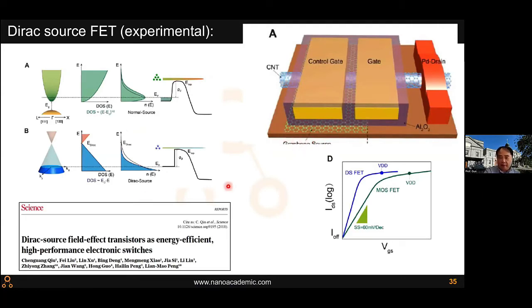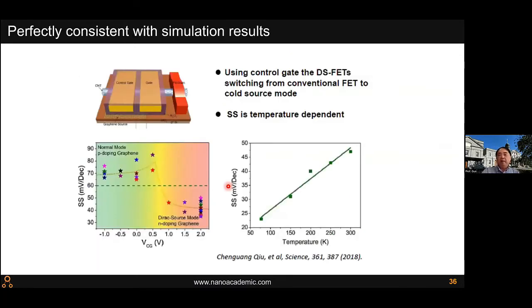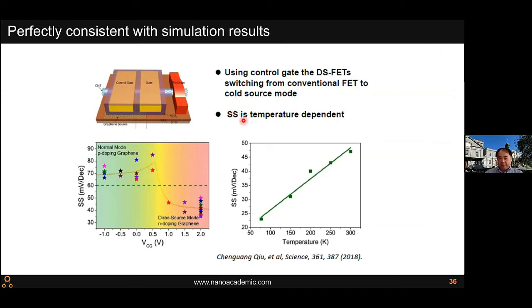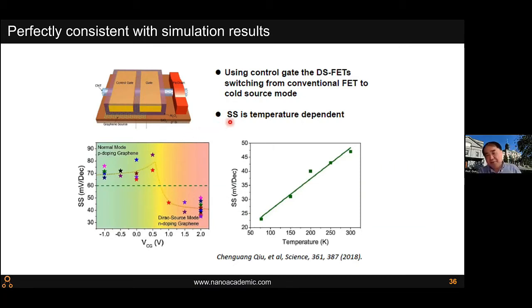This is a very nice discovery. The measurements agree well with the theoretical calculation. The important message is that graphene can be used as the contact electrode for field effect transistors, producing low-power transistors with very high on-off ratio. This could extend Moore's law for high-performance computing. We are collaborating with experimental groups to see whether we can produce an all-carbon technology that can supplement — not replace — silicon in certain technology areas.